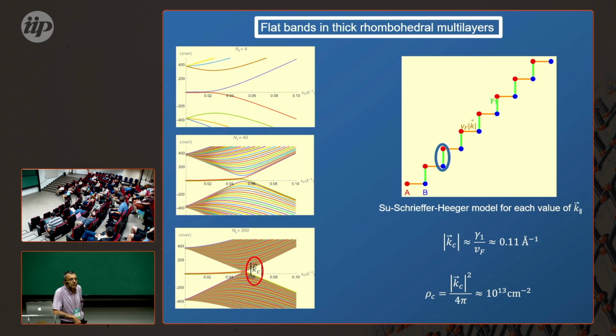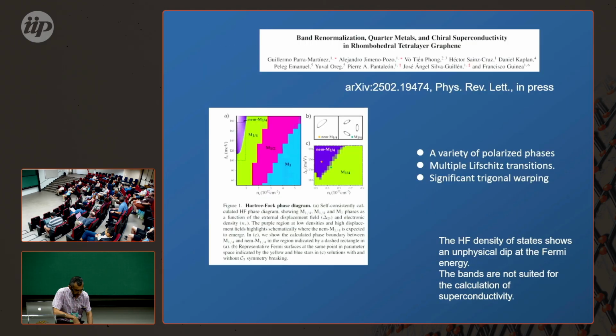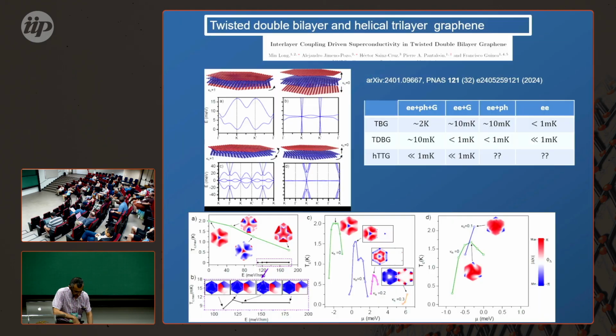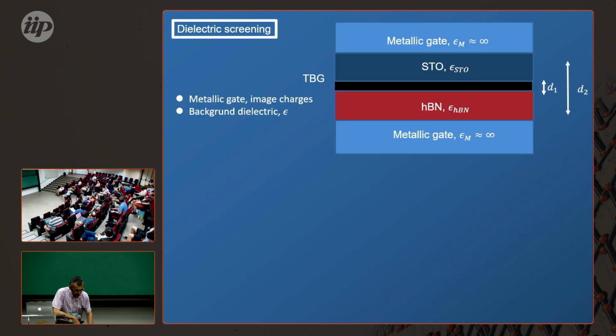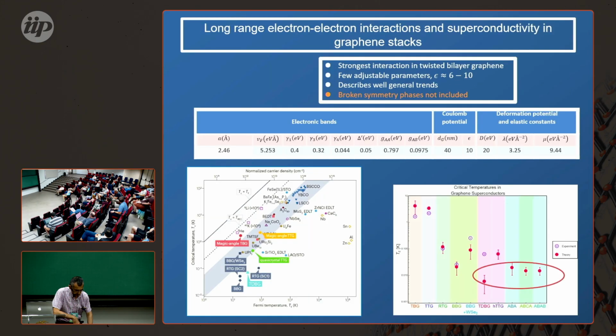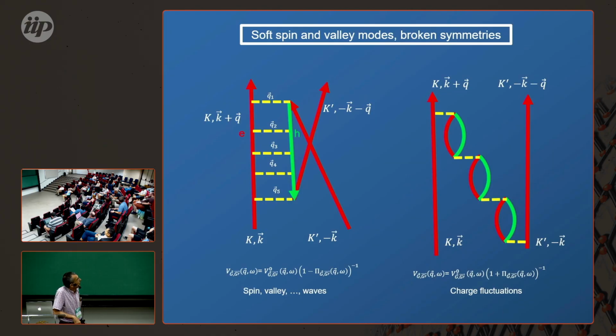Okay. The question will be a little bit technical, but I will accept a non-technical answer. When you do diagrammatics, when you do calculations, you essentially take bubbles and sum bubbles, justifying it by large N. On the other hand, if you look back into Kohn-Luttinger, Kohn-Luttinger was a way to also describe spin fluctuations, and for example, spin-mediated d-wave superconductivity. And this is a different set of graphs, maximally crossed diagrams, that give you interaction by spin. Maybe putting the connection to Lewis's talk, in your case, the idea is that spin fluctuations are totally irrelevant.